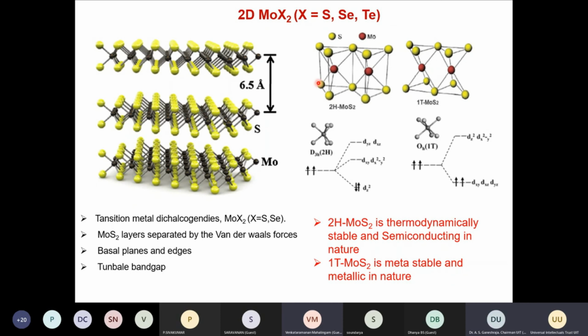MoS2, particularly molybdenum sulfide and selenide, can exist in two different phases. For example, the 2H phase, which is a semiconductor, and the 1T phase, which is metallic. The structure is slightly different for the two of them. One has D3h symmetry, another has octahedral symmetry. If you see, for example, it has 2 d electrons, so the splitting looks like this. So it basically has a very stable state compared to this one, because there is one electron less in this state. So the 2H phase is quite stable.